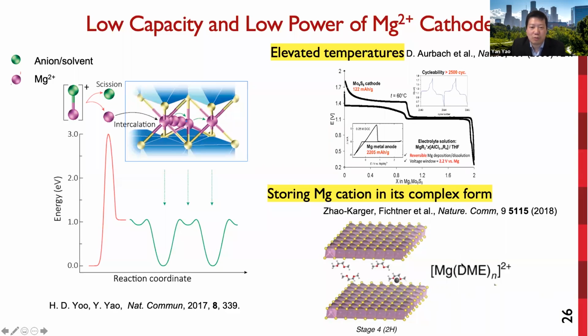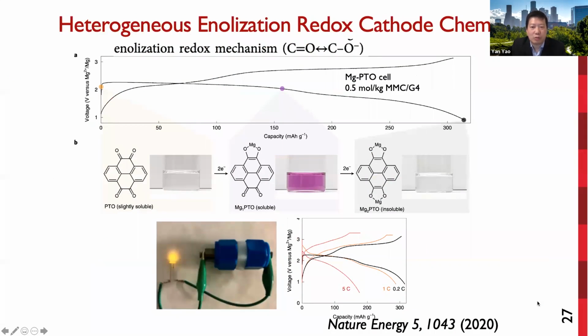Storing complex ions would lead to a limited cycle life caused by volume change due to co-insertion of the bulky solvent molecules. Therefore, the cathode materials require a new reaction mechanism to support fast magnesium 2+ storage. In our recent work, we have demonstrated a heterogeneous enolization redox cathode chemistry to circumvent the ionic dissolution and solid-state diffusion challenges.